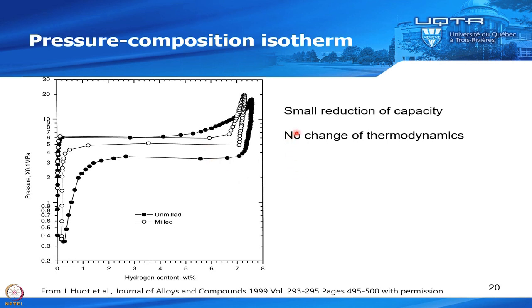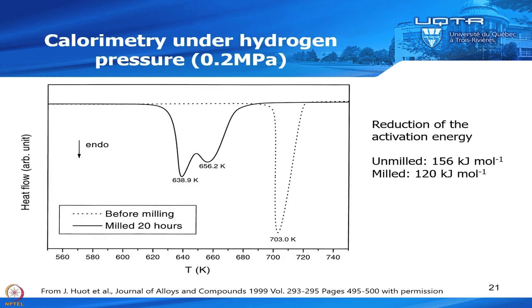Okay, but you see that you basically do not change the thermodynamics, you just change the kinetics, and you see a small reduction of capacity here after ball milling. So this is confirmed by calorimetry. So this is under hydrogen pressure, that was under 2 bar of hydrogen. So if you put your magnesium hydride and you start to increase the temperature, at one point it will desorb, and that gives you that peak, and that's the temperature of the peak. Okay, and if you ball mill, then you reduce that temperature because the kinetics is faster.